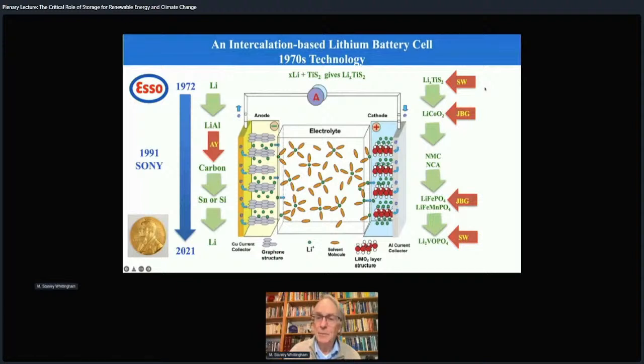On the cathode side, we started with the layered compound TiS2. John Goodenough was working on cobalt oxides, their magnetic behavior, and recognized they had the same structure. So he looked at their electrochemical behavior, and you all know the history. So all your cell phones are basically still lithium cobalt oxide. I mentioned earlier, cobalt is too expensive. So this same structure is now made up of nickel, manganese, and a little bit of cobalt, or in the case of Tesla, a little cobalt and a little bit of aluminum.